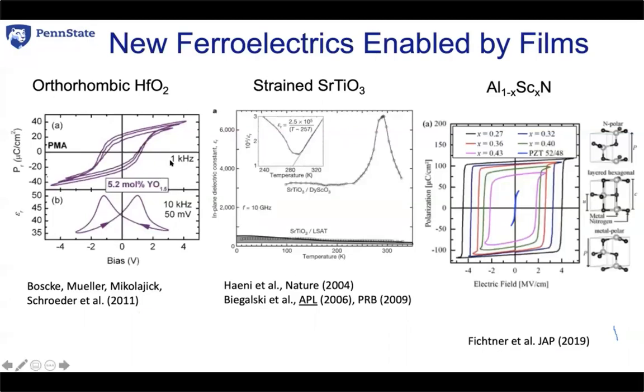Work on the use of strain, and I show here work on strained strontium titanate, where a ferroelectric phase transition temperature has been pushed to about 300 Kelvin in a material which is otherwise an incipient ferroelectric. That also led to major advances in the science and engineering of ferroelectric films. And then I'm an incredible fan of this work from the group of Fichtner on aluminum scandium nitride, where they demonstrated just a year ago that by destabilizing the wurtzite crystal structure through the addition of scandium, it is possible to take this material and develop really beautiful hysteresis loops.